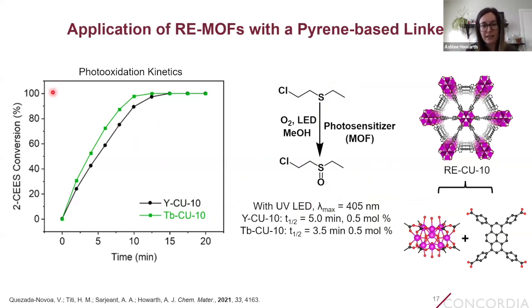And here you can see the conversion of the simulant versus time. And so what we see is that this reaction goes to 100% completion. It is selective to generate the sulfoxide. There's no production of the sulfone. And we see that the reaction is quite fast, with half-lives of 5 minutes and 3 minutes, depending on the analog of CU-10 that you use.